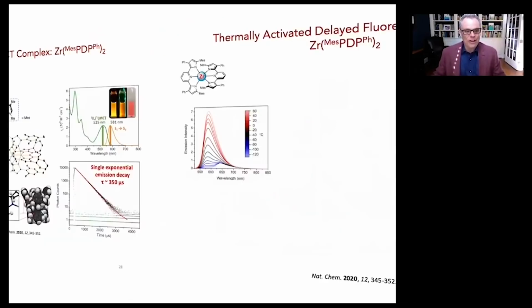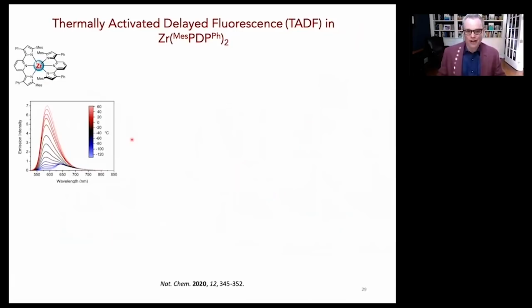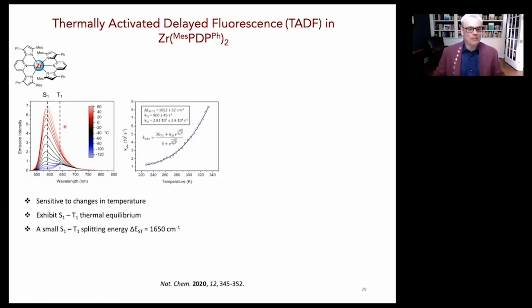So we naturally did what we do in my group. We dive into all the photophysics and we do the temperature dependence of this emission band. And what you immediately notice is if you go cold enough, all you see is the low energy part of that spectrum retained. And then what happens if you go higher? Well, as you increase in temperature, you're driving up the higher energy emission band. This is a classic example of thermally activated delayed fluorescence. And basically the triplet phosphorescence is here, the singlet energy is right there, but you can fit the temperature dependent data and you get exactly the same energy gap as you measure experimentally by the spectra.